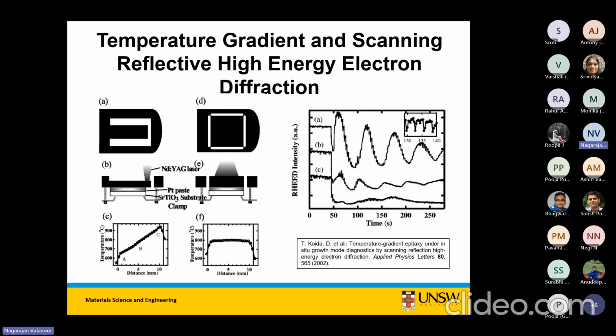And the other thing that we use, not in my lab but in the one dedicated to LAO-STO, is the scanning RHEED. I'm not sure whether the RHEED guns that you have here are spot or scanning. But if you have scanning, the advantage is that you can choose 7 or 8 locations, and each one will give you a RHEED pattern. So you just choose the best RHEED pattern for your paper. The beam actually rasters over the RHEED gun, and it is also now rastering over the sample. So it's quite an interesting approach to look at growth.